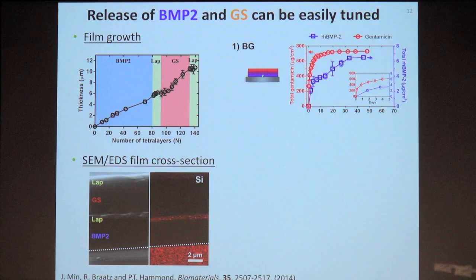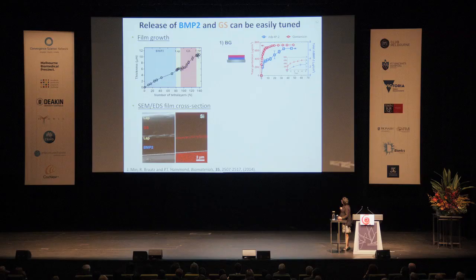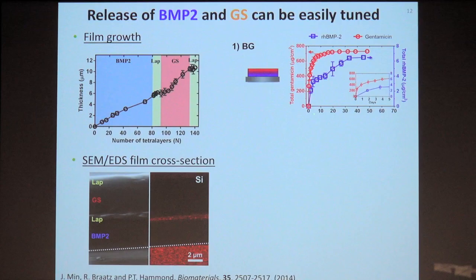When she has no diffusion barriers in between her BMP2 and her gentamicin sulfate, here BMP2 is blue, gentamicin sulfate is red, the gentamicin comes out very rapidly, a large amount at once. It's excellent for eliminating an infection, but then it's sort of gone after the first 10 days or so. BMP2 comes out, it's separated, but it's not separated a lot, just a little bit from the gentamicin sulfate, so that you get maybe about a half of it being released somewhere in a 10-day period.